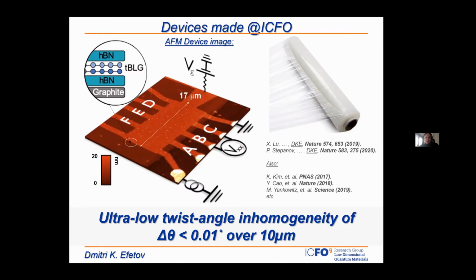So the main challenge in the fabrication of these devices is keeping them bubble free and without any folds. Right now, probably the best devices which we ever made can be relatively homogeneous, where the inhomogeneity of the twist angle is only 0.01 degrees over a length scale of 10 micrometers. But these are really exceptional devices.